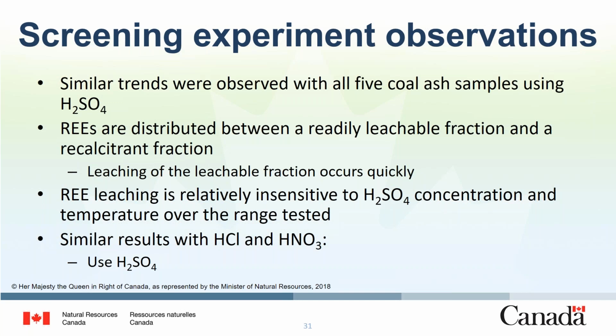We also tested these materials with hydrochloric acid and nitric acid, and the results are very similar. So we've selected sulfuric acid for further testing because of the relative cost and the fact that recovering REEs from sulfate media is fairly well documented.